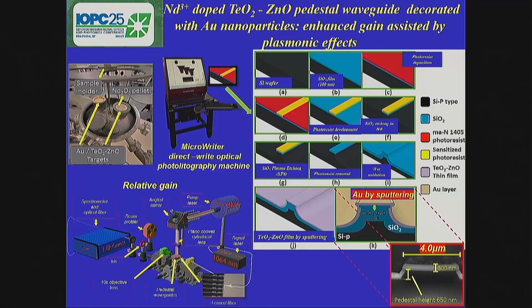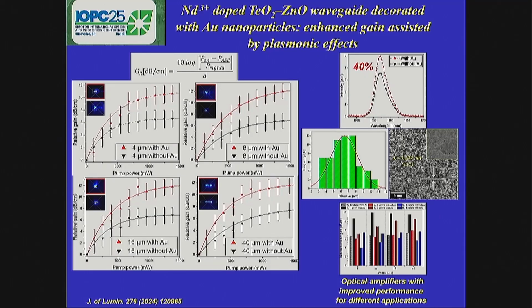And then we have here the results obtained. In fact, we have relative gain for different pump powers, for waveguides prepared with different widths: 4 micrometers, 8, 16, and 40 micrometers. The black curves are those related to the waveguides that were prepared to be used as reference, in this case without gold nanoparticles, and the red ones are related to the waveguides decorated with gold nanoparticles, and we can observe an enhancement in all cases that reaches up to 8% for the waveguide with 8 micrometers width. All these results are correlated to the photoluminescence enhancement that is attributed to the enhanced local field around these gold nanoparticles that increase the density of the neodymium ions that are excited, the well-known plasmonic effect.